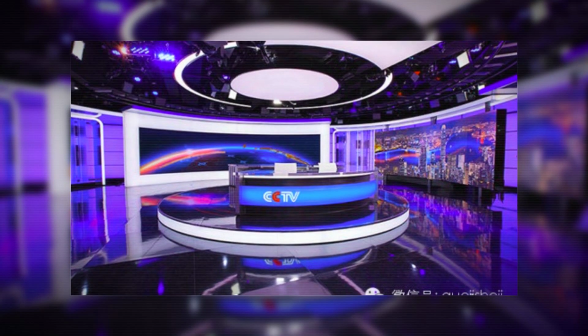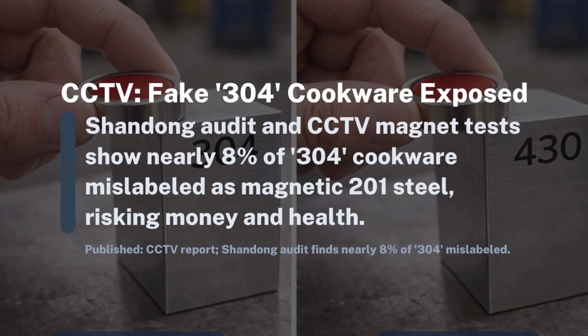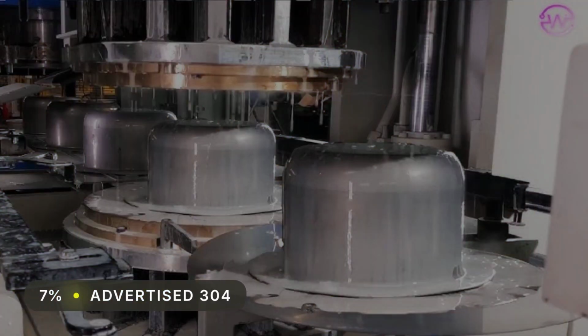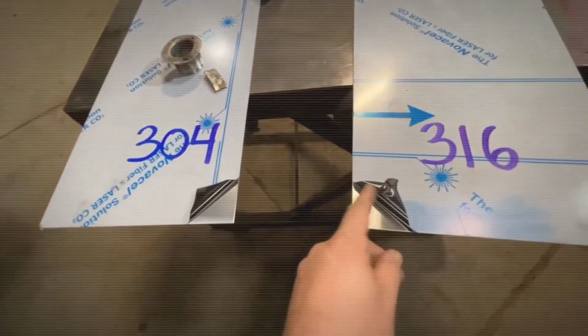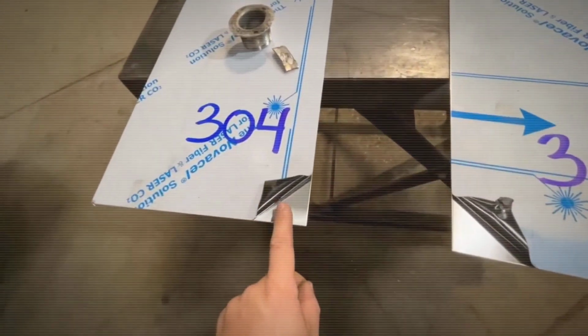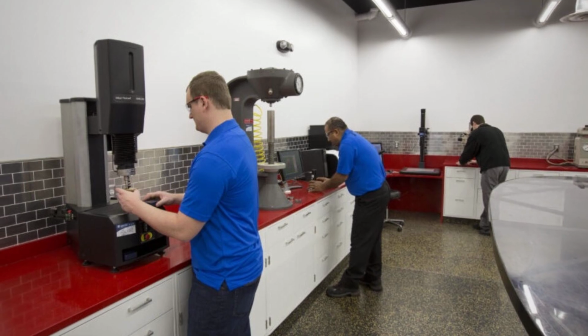In 2024, China Central Television reported that nearly 8% of stainless steel kitchenware tested in Shandong failed to match its label. 8 out of every 100 pans or bottles advertised as premium 304 were actually made from lower grade 201 steel. The chemistry tells the story.